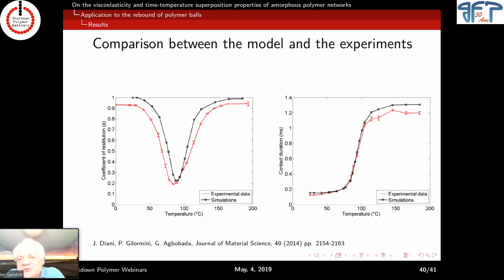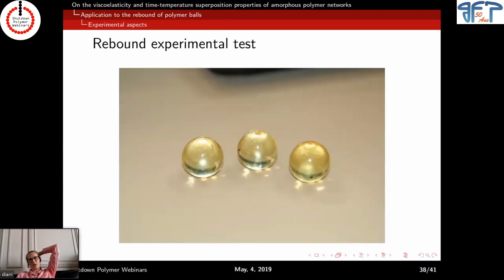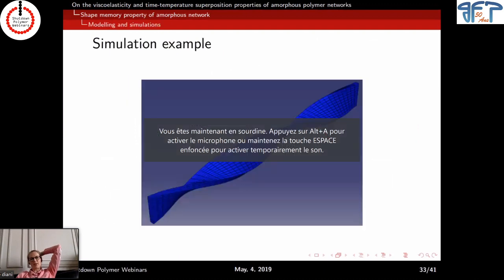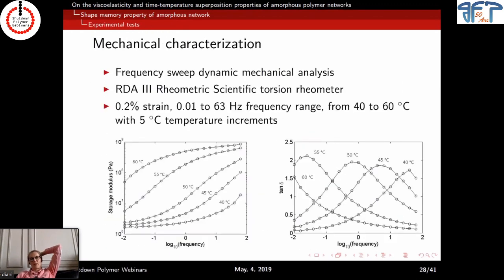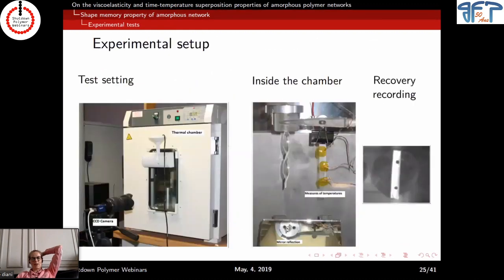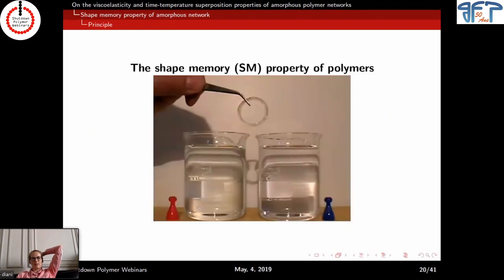She was asking if you tried different cross-link ratios, because you show us 10%, but is it a parameter you varied in your simulation? 10% is actually quite a lot. It's a tight network. So we tried different things, and it depends on your cross-linker, I guess, but for example, we did recently some IPN. We were interested in the viscoelasticity of IPN, and so we had 2% molar mass.